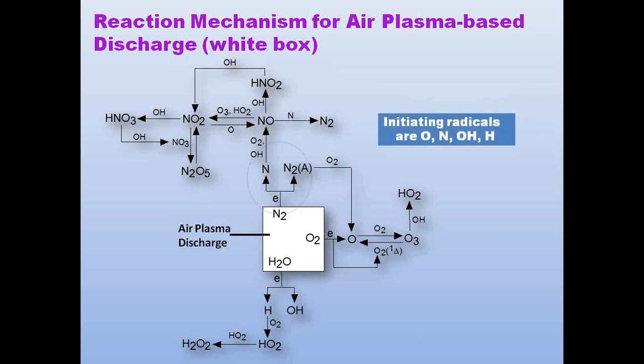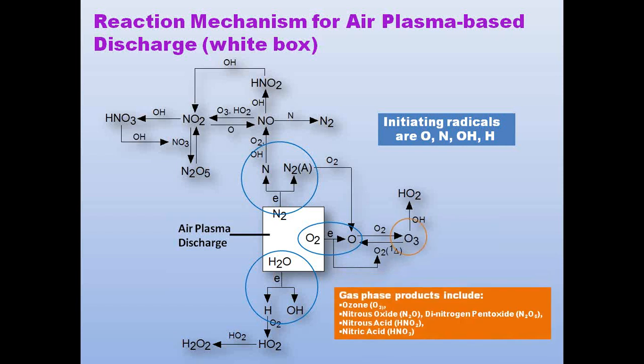After that reaction takes place, initially you have initiating radicals that come to bear just outside of the initial discharge mechanism. So then again, you have radicals such as atomic oxygen, nitrogen, OH groups, hydrogen groups that are all beginning their pathway to the surface of the material. Continued reaction ultimately generates gas phase products such as small amounts of ozone, the oxygen molecule associating and dissociating in air. You have nitrous oxide, nitrous acid, nitric acid, all of these functional groups that can play a key role in their small quantities of functionalizing a surface.